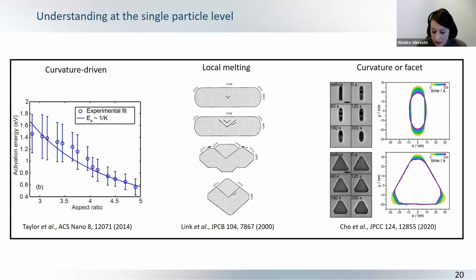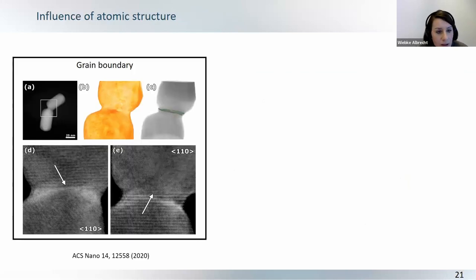And I would like to show you one example of where this atomic engineering can actually be interesting, and this is coming back to these welded nanocrystals, gold nanorods, where we saw with electron tomography that we have one crystal defect at the interface. So, there was either a grain boundary, as shown here, or a dislocation, but it was always one defect at the interface.